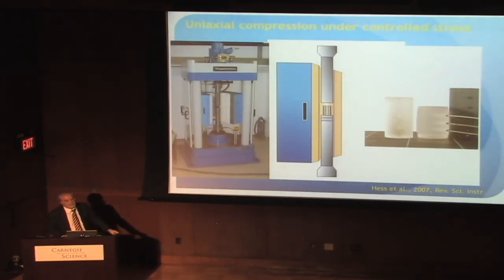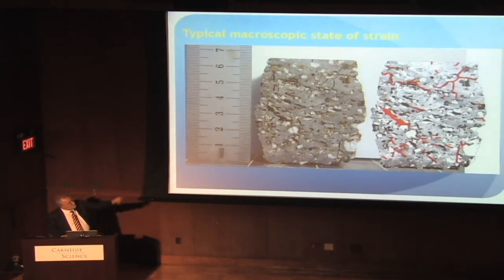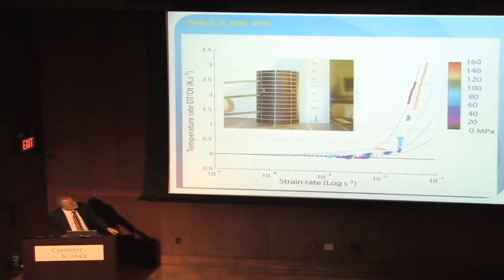The viscous heating effect has now been done experimentally. It's relatively easy to do. You simply ram thermocouples into a sample, squeeze it at particular rates, and see how much viscous heating you obtain. The samples look barrel-shaped afterwards. There's a certain degree of homogeneity of the bulk deformation, even though, as you see, these samples are horribly heterogeneous, having crystals and cracks and bubbles in them.